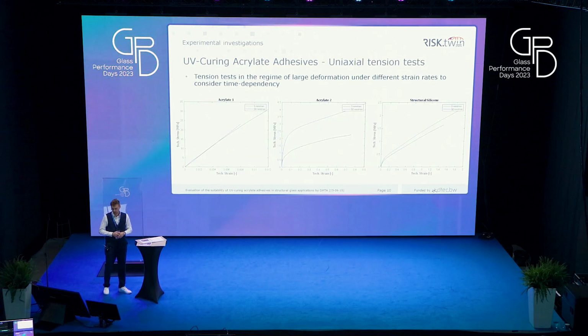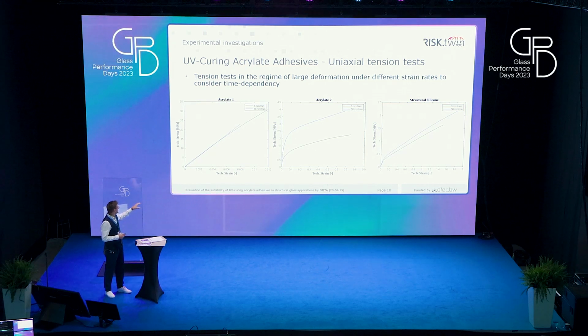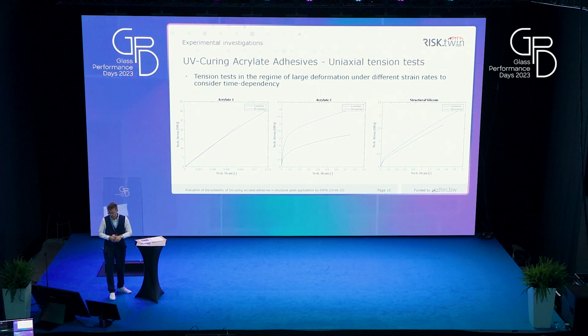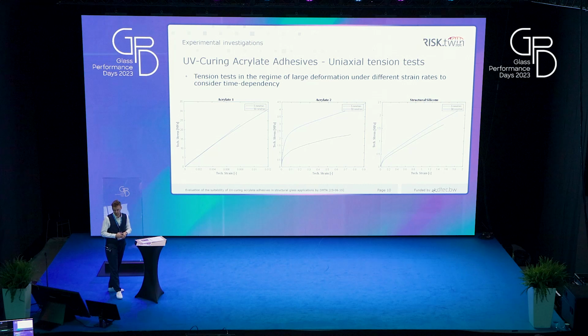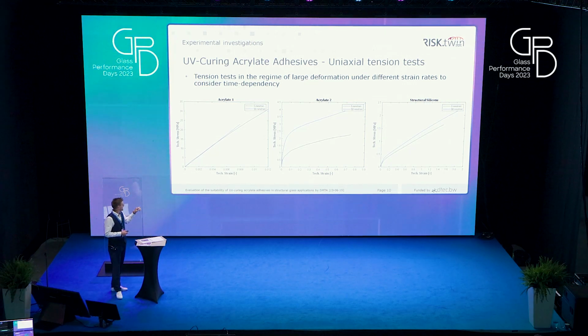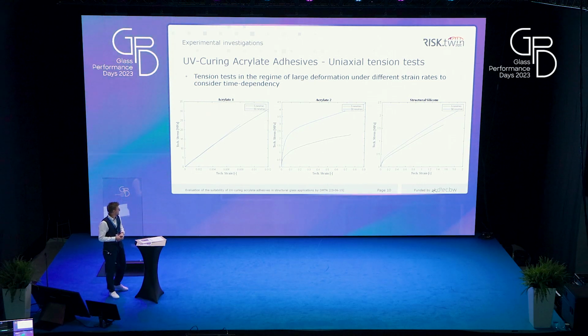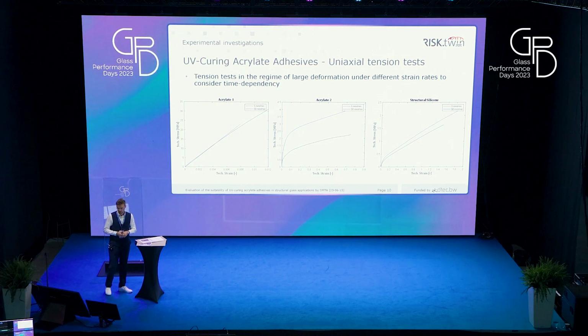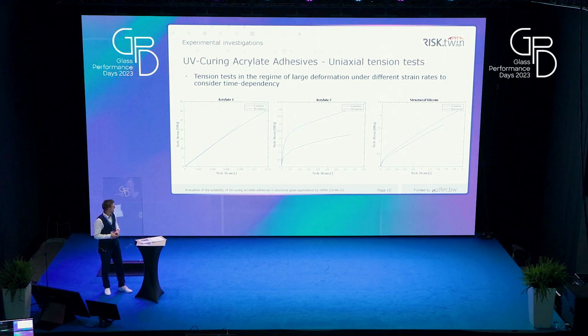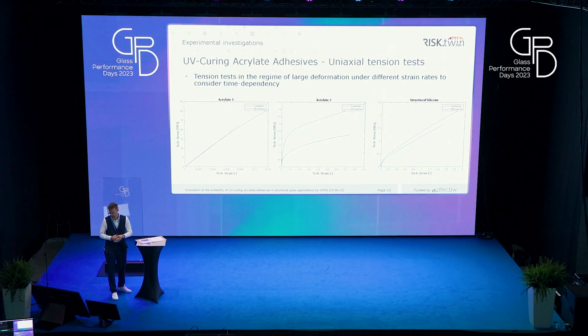Let's have now a closer look at these tests, where again, acrylate 1 is the very stiff one, and acrylate 2 is the red one, which was in the middle. And we tested them in tension mode under different strain rates to consider their time dependency. And as you can see, with the very stiff one, the curves almost lie exactly above each other, so there's no time dependency. In contrast to acrylate 2, where we have a significant difference between the two curves, so the adhesive reacts much stiffer under faster deformation.